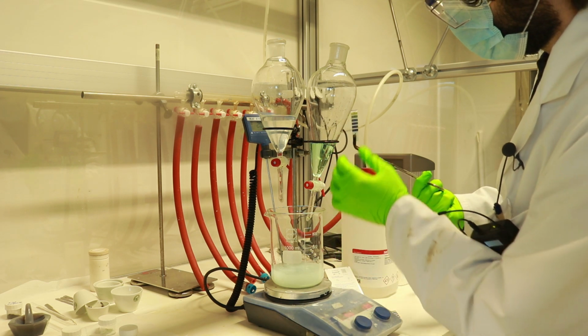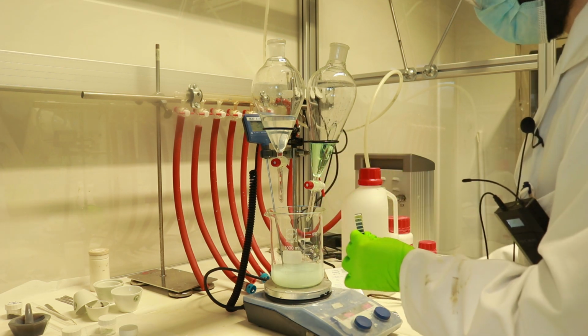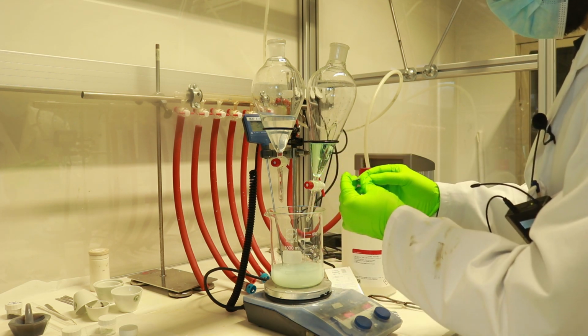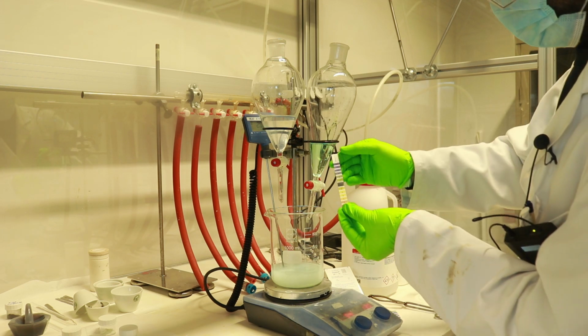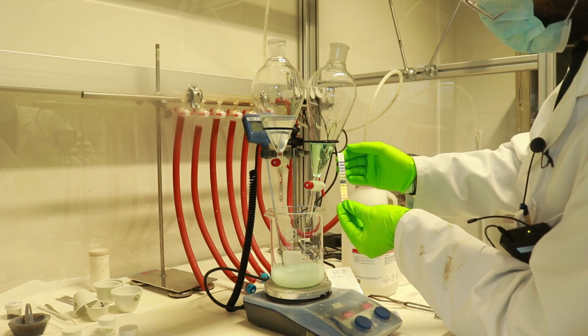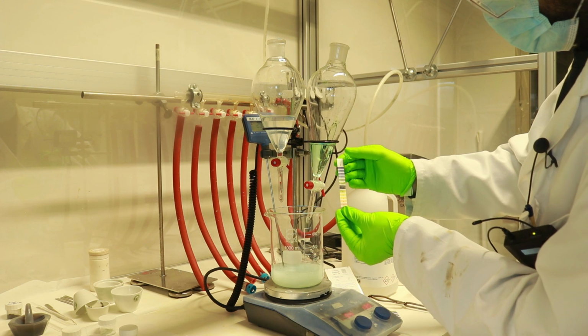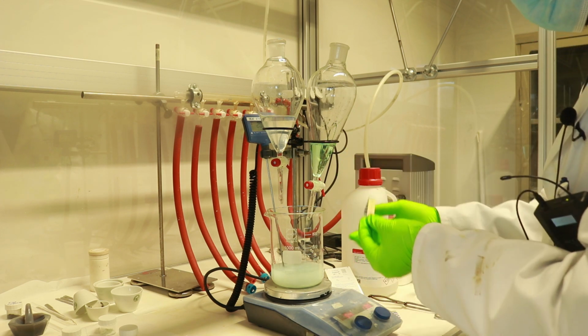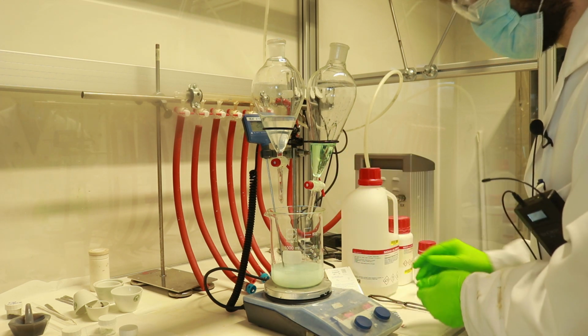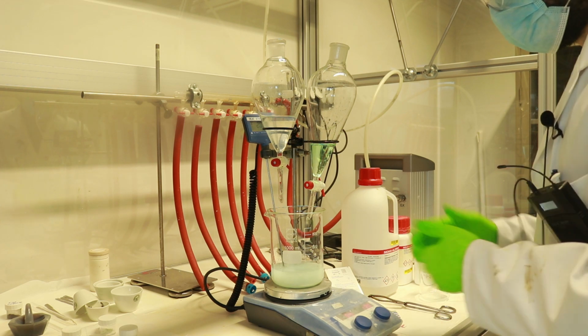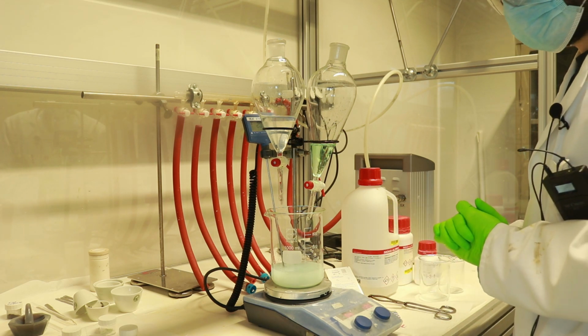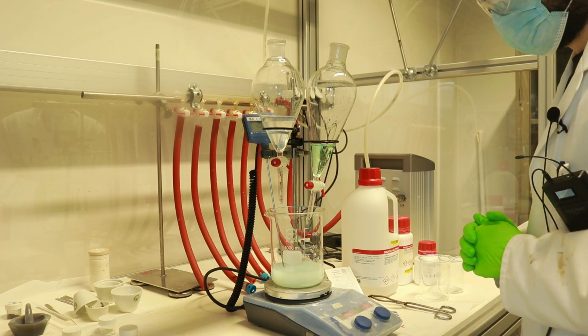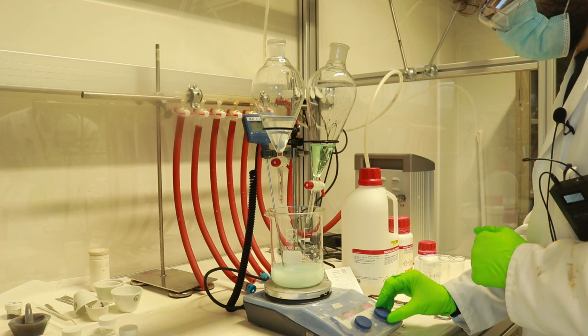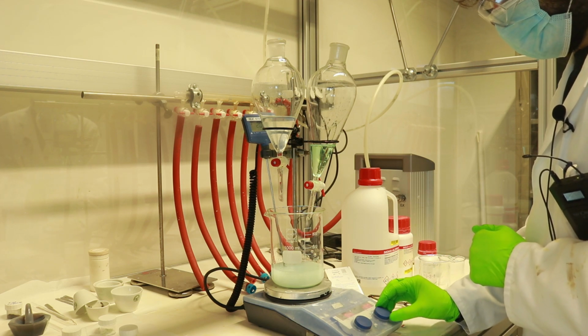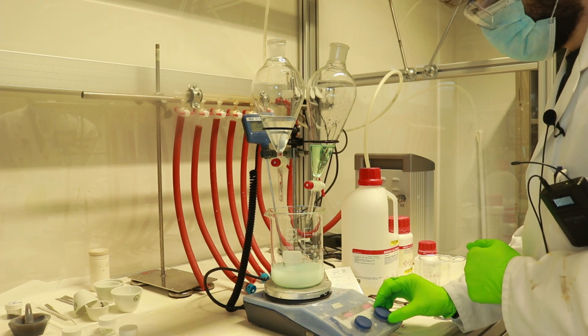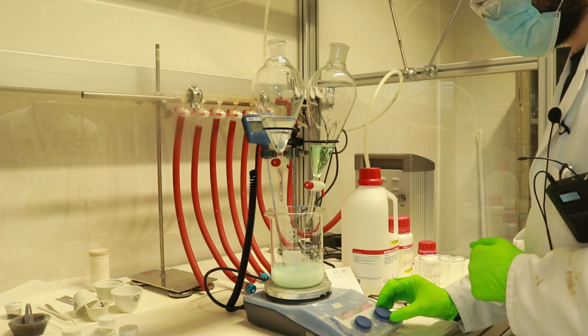And indeed, this indicates that the pH is around 9. This means that the rate at which we are adding both solutions is acceptable, and every few minutes it's advised to check the pH again, to make sure that it's controlled. And as the liquid fills up the beaker, we'll probably need to increase the stirring rate.